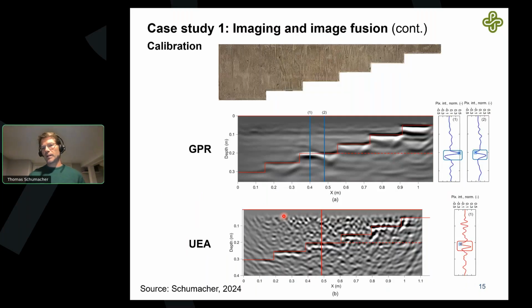But here's what we came up with in my research group, what these images look like. This is an example of a stepped concrete specimen. It's unreinforced. We take the measurements on top, and properly calibrated, we can see these steps showing up in the image. So now we have a digital cross-section of this. You can also see something interesting happening on this step. We have this first reflection that is bright in the beginning and then dark in the second part, and for all other steps, the dark band is before the bright one.